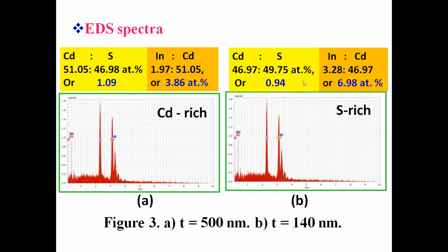Now the thinner film, the ratio of cadmium to sulfur in this film is 46.97 to 49.75 atomic percent, or 0.94, so this film is S-rich. The ratio of indium to cadmium in this film is 3.28 to 46.97, or 6.98 atomic percent. So this film, the thinner one, has less cadmium but more indium, so indium will balance its n-type conductivity.